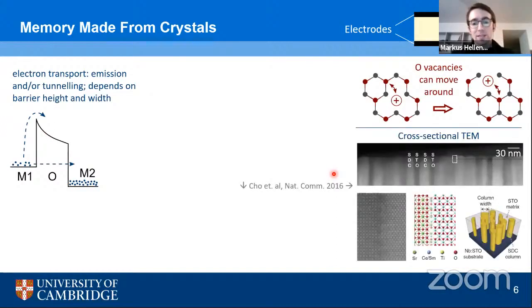So what we can do with this technique that I showed before, pulsed laser deposition, is to make such heterostructures here. So we can make pillars of one crystalline material inside a matrix of another crystalline material. And why we do that is that we can combine materials such that inside the pillars, these oxygen vacancies can move around relatively easily, but they cannot do so in the other material. So by this, we can define channels along which the oxygen vacancies can move back and forth.